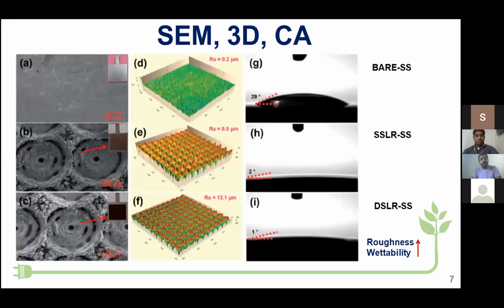This slide shows the 3D and contact angle of the bare, single side, and double side laser rusted stainless steel. Figure A corresponds to the bare stainless steel, which has a smooth surface with a gray silver color. When the pre-cleaned stainless steel is irradiated on a single side, the perfect honeycomb texture has been drawn over the substrate, which is confirmed visually through the formation of a light brown colored layer, which is nothing but rust. The main constituent in stainless steel is Fe, which undergoes oxidation to its oxides.